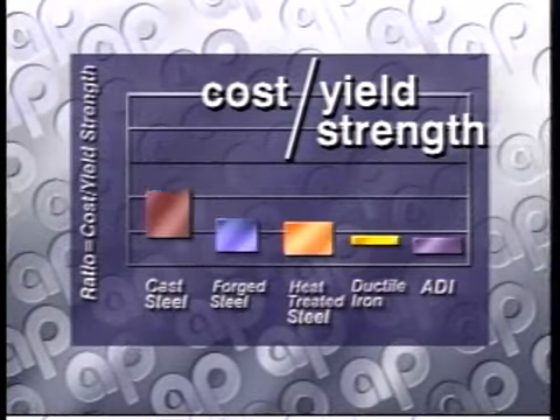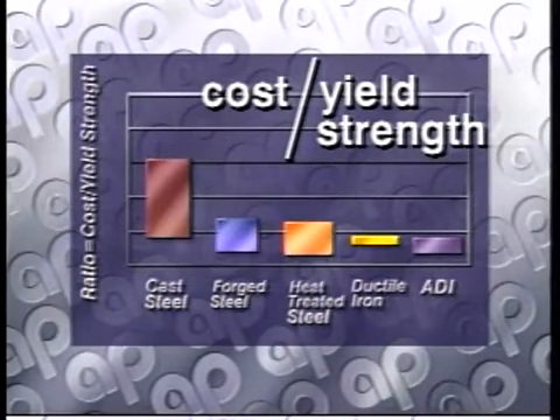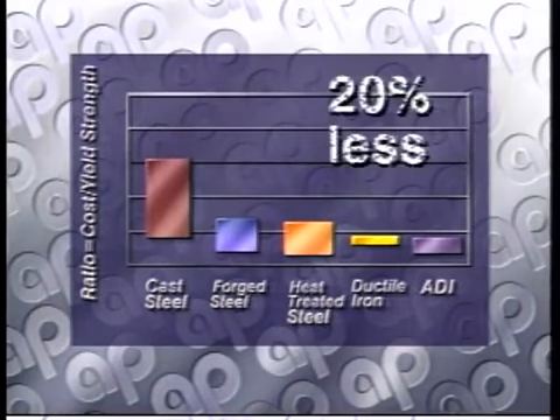While prices vary worldwide, on average, ductile iron castings cost significantly less than steel castings or forgings. In North America, when the cost of Austempering and transportation is added, the price of an ADI component is typically 20% less than a comparable steel forging or casting. Additional savings are realized by machining in a soft, as-cast condition.